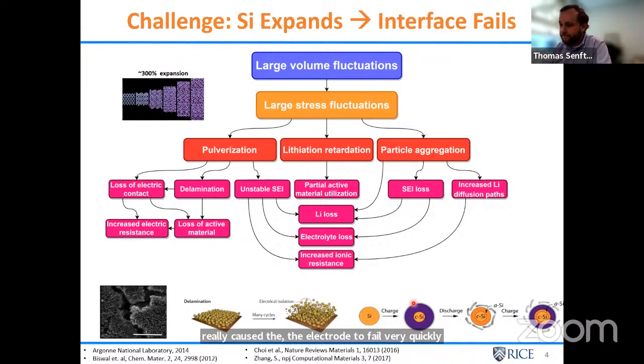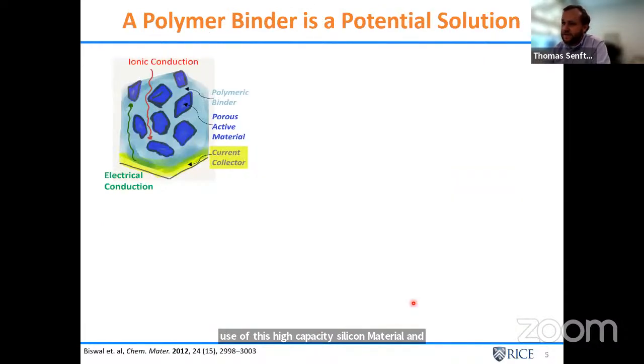So we want to effectively use simulation to understand what's happening at these interfaces, to understand how we can potentially mitigate some of these stress fluctuations and the stress buildup so that we can have stable interfaces and really enable the use of this high capacity silicon material. And the strategy that we're gonna take is to take the silicon and embed it in a polymer. And this is a strategy that's been around for a while.